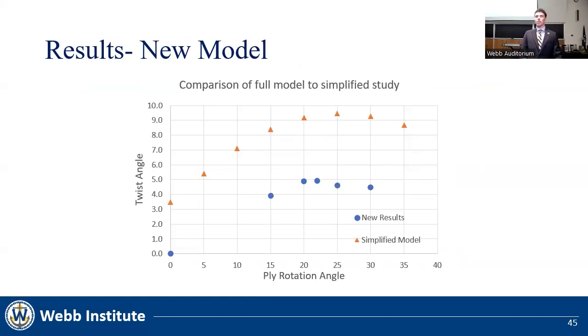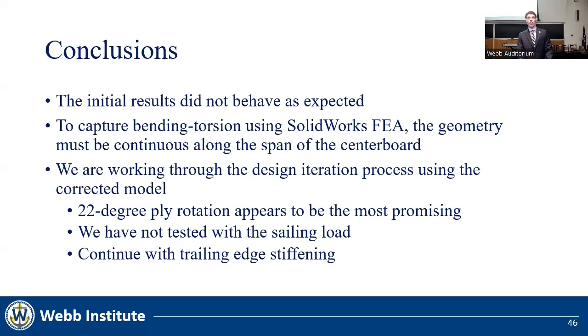Here are the results of the simplified study side by side with our new results. The difference in the magnitude of twist is caused in part by the foil-shaped cross-section in the new results, and in part by the fact that the new results involve the use of thicker laminates at higher ply rotation angles. In conclusion, the initial results did not behave as expected. After performing additional analysis, we concluded that in order to capture bending torsion coupling effects in SOLIDWORKS FEA, the geometry must be continuous along the span of the centerboard.